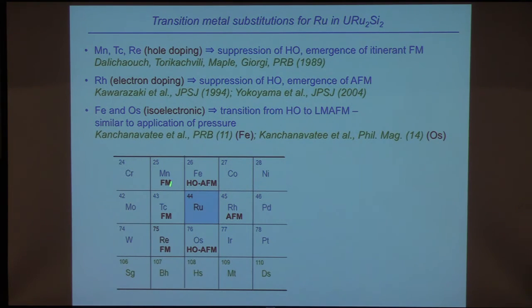So this dopes the system with holes. And what this does is it suppresses hidden order and gives you the emergence of itinerant ferromagnetism. And this we discovered back in 1989, but have studied in more detail since then. For rhodium, it's known from work in Japan that you can then dope the system with electrons, and this suppresses hidden order, and you get the emergence of antiferromagnetism.